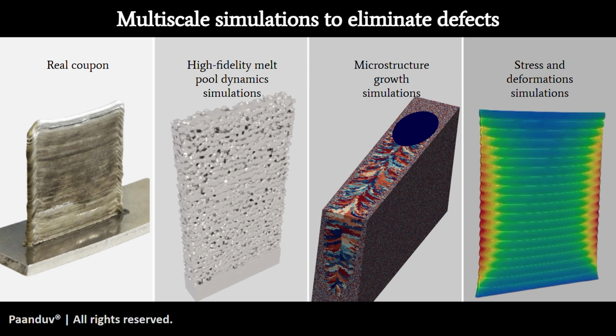The second approach, which can run hand in hand with the experiments and significantly take off the load from the experimental work and the errors associated with this, is the high fidelity multi-scale simulations, which can eliminate defects from build. So what we see here is a real coupon on the left hand side, and again these are all representative images. They don't necessarily validate each other. The image on the left hand side is a thin plate, a real coupon printed using 3D printing. Then the second image is that of a high fidelity melt pool dynamic simulation for a 20 layer thin plate build, simulated using AM PravaH.